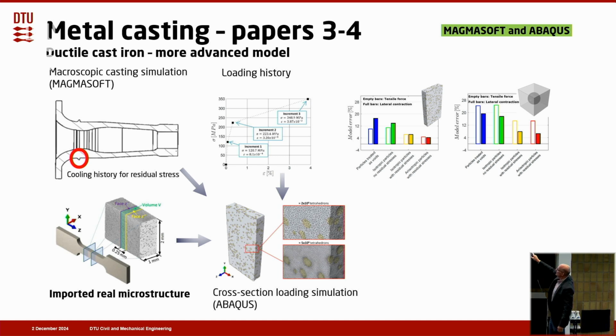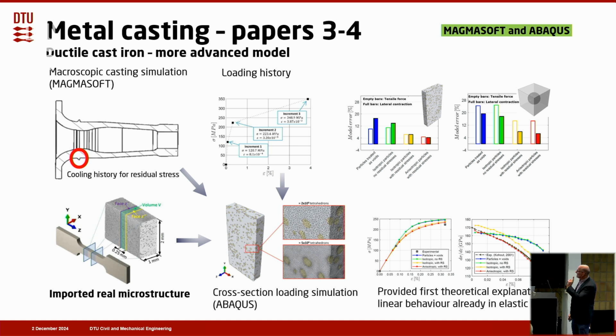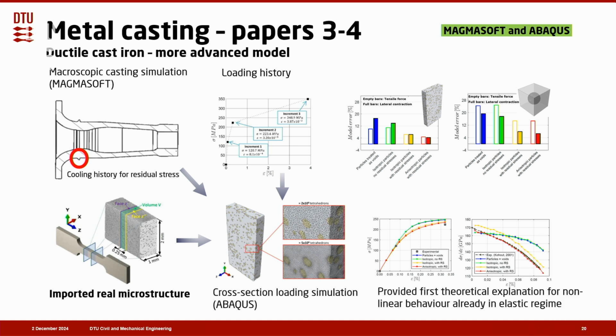Okay, anyways, but you can see the figure to the left, the two reddish ones, they are around 3–4% from the experimental values, and this was with the advanced model. And what was really interesting here was that we could then provide the first theoretical explanation for the nonlinear behavior already in the elastic regime for this material. So you needed to look into the micromechanical behavior of the material to say something about its behavior macroscopically when loaded in real life.